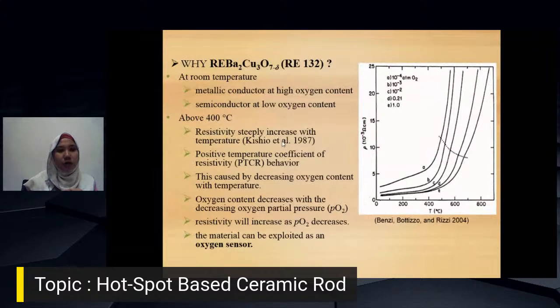When talking about this ceramic compound above 400 degrees Celsius, the resistivity increases with the temperature. When the temperature increases, the resistivity also increases. That is related to the positive temperature coefficient of resistivity, PTCR behavior, caused by the decreasing oxygen content with the temperature. When the oxygen content is very low, the positive temperature coefficient of resistivity increases with the temperature. When the oxygen content decreases with the decreasing oxygen partial pressure, which is equal to the concentration of the oxygen, the resistivity will increase as oxygen partial pressure decreases. So this material can be explored as an oxygen sensor.